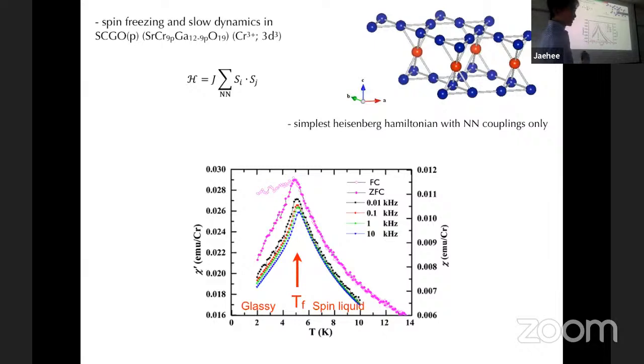Another system that was very hot back in the 1990s, in fact, when I was a student, was my thesis project. This one is called SCGO. The magnetic ions are chromium 3+ ions, and the magnetic ions form what I call a bipyramid lattice. Basically, when you have a three-dimensional pyrochlore lattice and view it along the 1-1-1 direction, you can consider it as a triangular lattice, Kagome lattice, triangular lattice, and this is continuously repeating. So we can take the Kagome lattice, triangular lattice, and another Kagome lattice, and that's it. We can have these three layers.